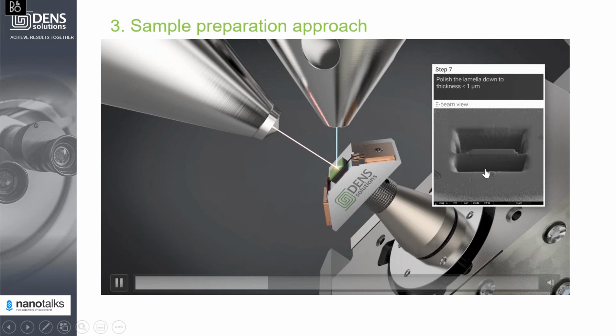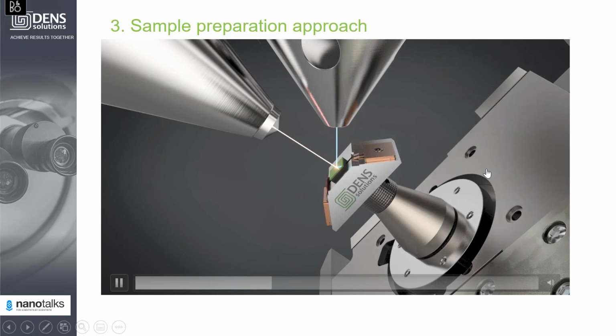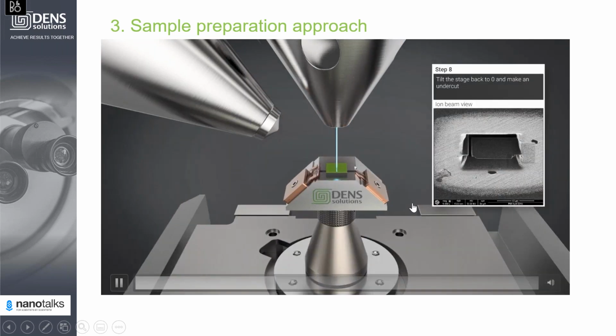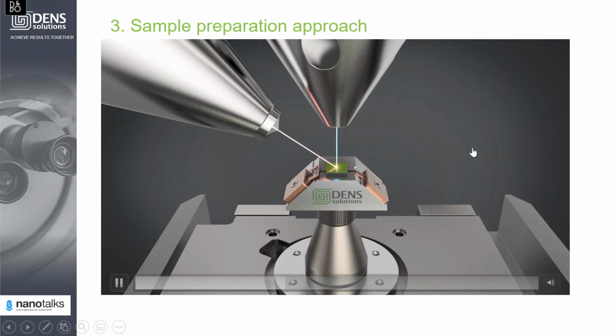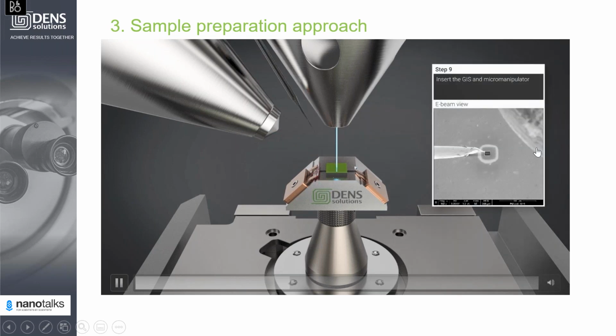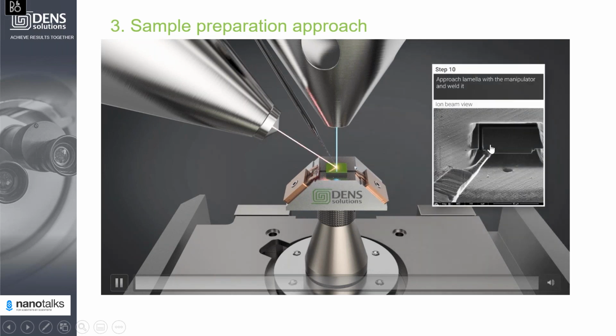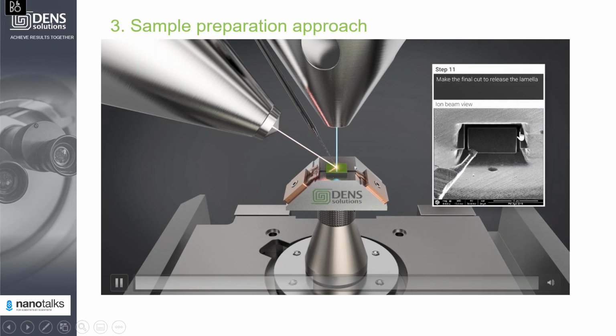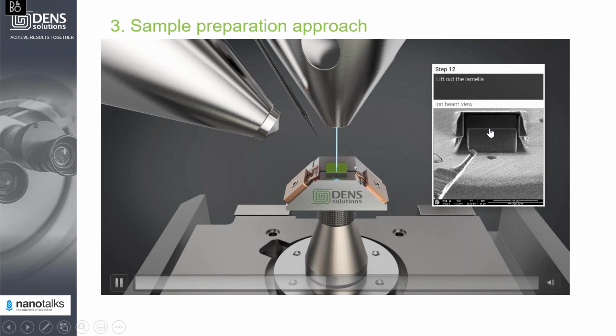Afterwards, you polish the lamella a bit after the rough cutting. You go back to zero tilt and make the undercut. So you can see here. You insert the manipulator and the GIS. You approach the lamella, you do the welding. You make the final cut to release the lamella. And then you do the lift out.